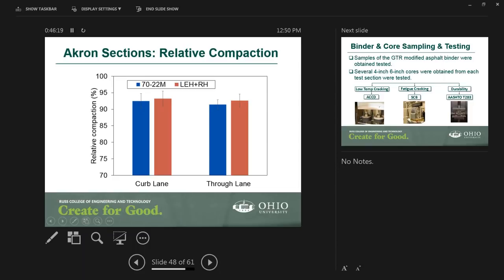Again, the relative compaction. We had four lanes, two lanes in each direction. So we had the curb lane and the second lane, and in both cases, based on both the testing with coring as well as the testing with the nuclear density gauge, we had a relative compaction of the GTR higher than the polymer modified. Again, it was a slight difference, but there was no problem in the compaction.